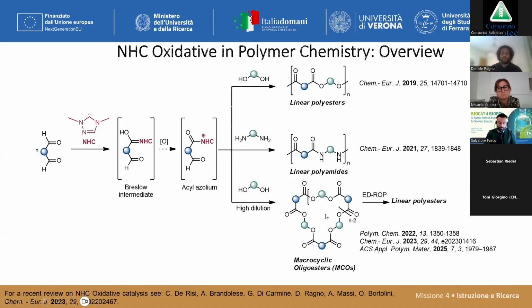These are all works from the group, providing new solutions, new strategies in the synthesis of polyesters, polyamides, and also working with dilution conditions, shifting the selectivity towards macrocyclic oligoesters that are very valuable intermediates for entropy-driven ring opening polymerization to afford very high molecular weight polymers.